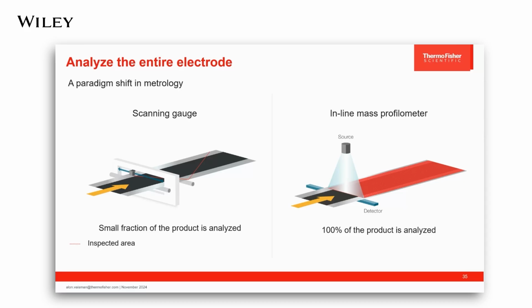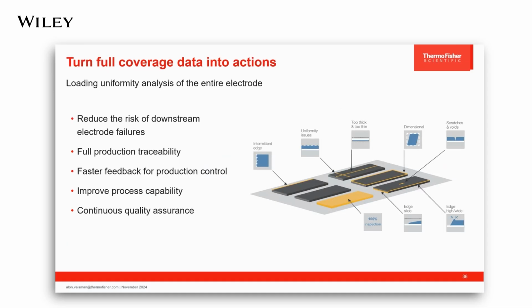Mass profilometry, on the other hand, captures the complete profile nearly instantaneously, every millisecond. It produces a record of the entire electrode roll and makes the information and results available in real time to help make process decisions and monitor quality. Mapping the entire electrode enables one to get a better understanding of the coating process performance. Edge features are analyzed in greater detail, and it becomes possible to identify spot defects like streaks, divots, high or low loading spots.